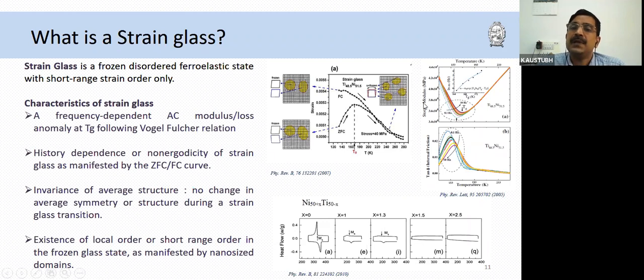So if you plot, for example, the storage modulus as a function of frequency, if you measure storage modulus and plot it, then you will see that there is a frequency dependence to this characteristic feature, which is identified as the transition temperature. And this transition temperature will follow the Vogel-Fulcher relation. That is one characteristic. The second characteristic is that the field cooled and zero field cooled curves, strain curves, will show bifurcation, and there will be an invariance of the crystal structure across the transition. That means if I record a differential scanning calorimetry, then the typical exothermic, endothermic peaks or features will not be seen. Instead, you will see just a straight unfeatured line.